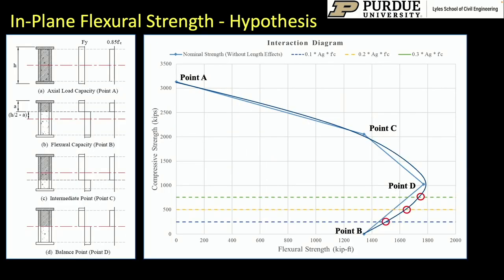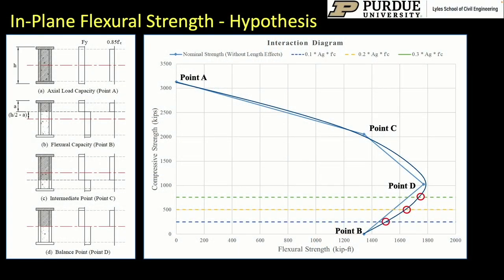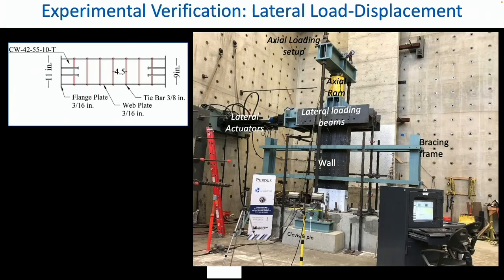When you combine this with axial compression, the in-plane flexural strength is calculated using the recommendations that are typically used for composite columns or composite beam-columns, which corresponds to the axial compression point A, the flexural capacity point B, the balance point D, and of course point C, which has the same moment capacity as point B. You can develop the PM interaction for this composite section, kind of similar to the way you do it for reinforced concrete, but using composite section principles, and those have been identified here. So depending upon if you have an axial load in compression of about 10%, 20%, or 30%, you can have different in-plane flexural capacities, which we'll talk about in just a moment.